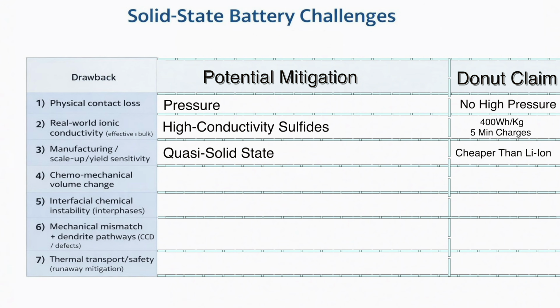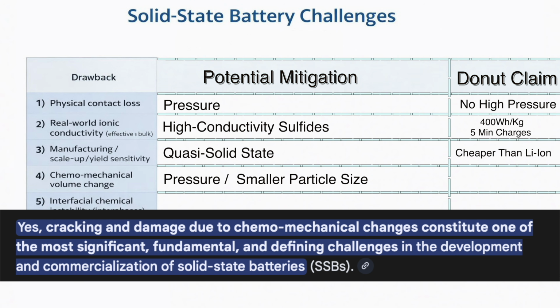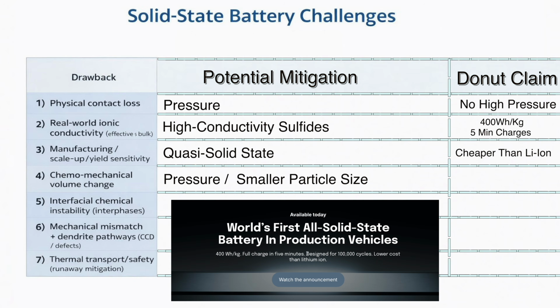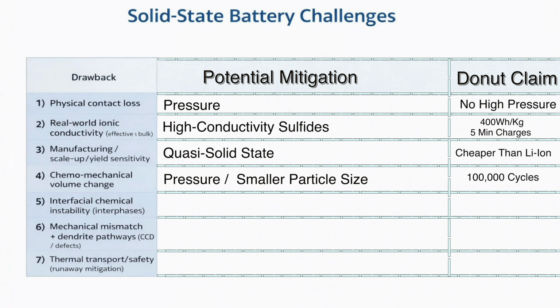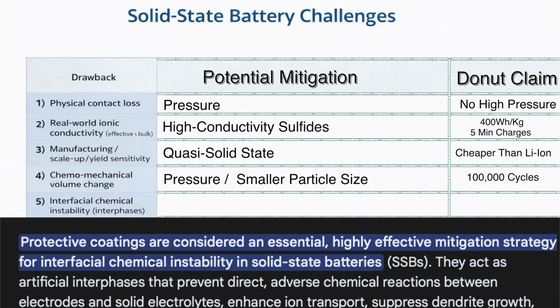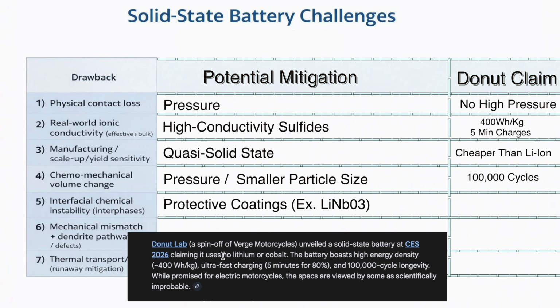Chemomechanical change is reduced with pressure, as well as small particle size. This drawback is a real-world failure constraint. Cracking and other damage is difficult to avoid in rigid solids. Big shocker there. Despite this, Donut claims 100,000 cycles. For interfacial chemical instability, where different solids don't get along at contact points, currently the best mitigation is protective coatings. An example being lithium niobate, I hope I said that right, or LiNbO3. But Donut claims no lithium, and again, a 5-minute charge time.